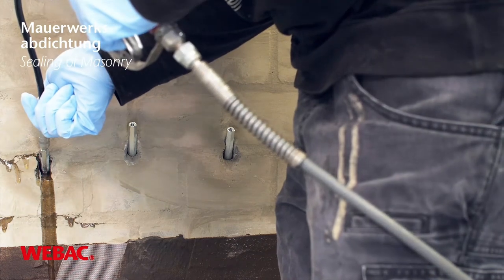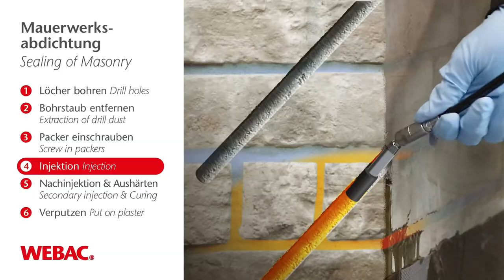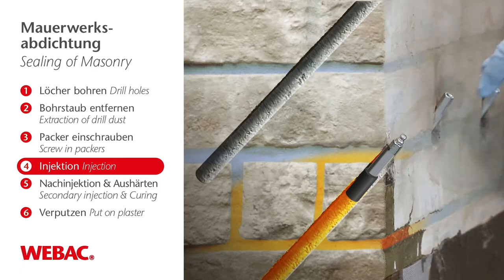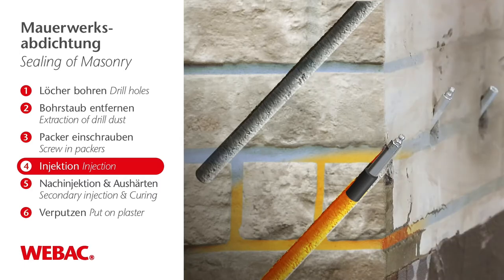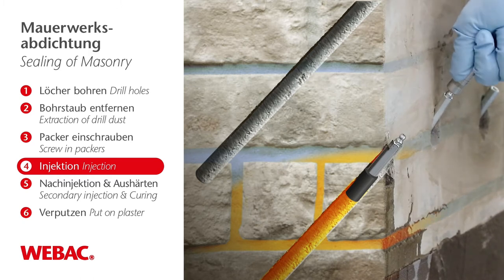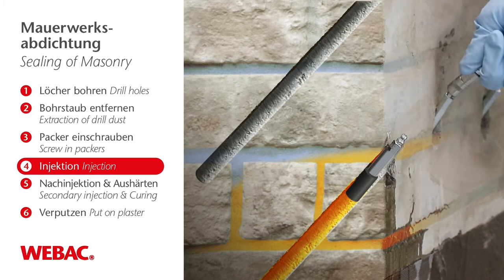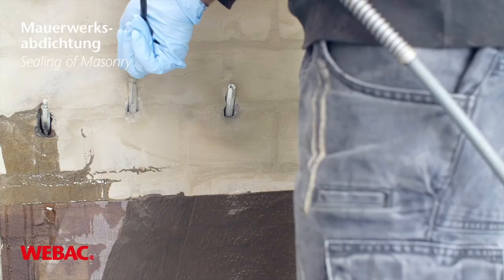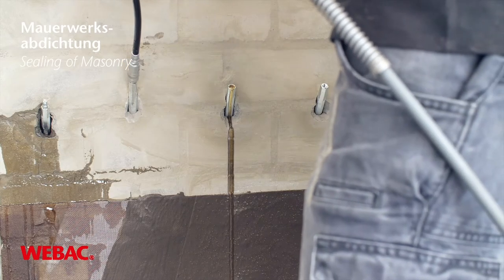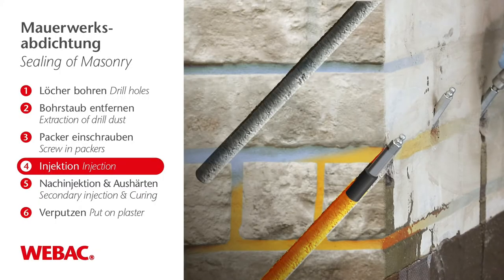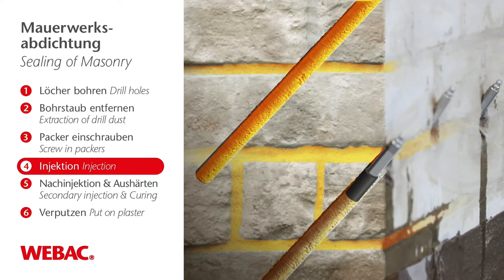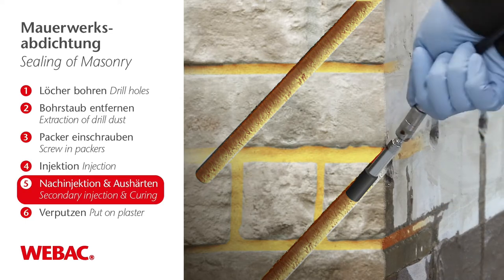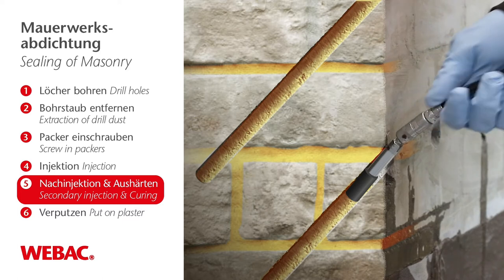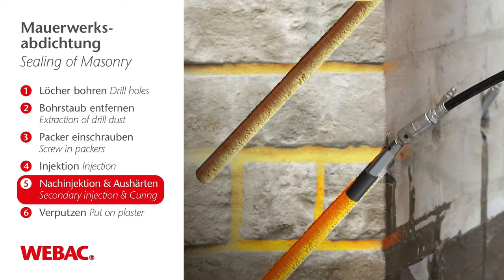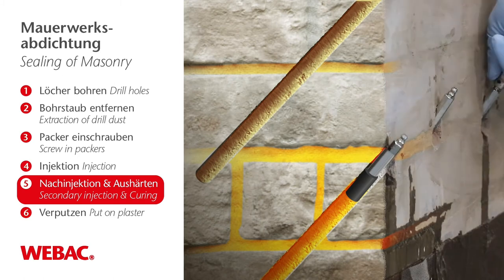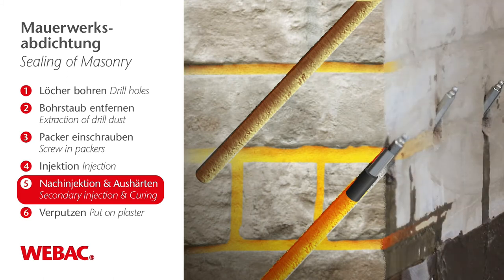There you see the injection process. Then you go from left to right, from right to left, however. And you see it very well at the joint at the bottom that the material is coming out. And there you see the material is coming out at the next bore hole. This is for you the best visual control that the material was penetrating along the mortar joint and filling it.